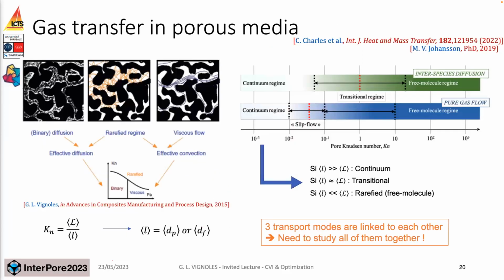And the other part of the modeling is to address gas transfer in these porous media. In this case, we have basically three types of possible gas transfer, which is diffusion, interdiffusion of gases of different gases. You have viscous flow, which is the usual Darcy regime. And in the middle, you got the rarefied regime that's called Klinkenberg or Knudsen flow or whatever. So we have 3 transport modes and they are linked to each other. So we chose to study them all together, even though in most cases, for example, Darcy flow is not important in CVI.